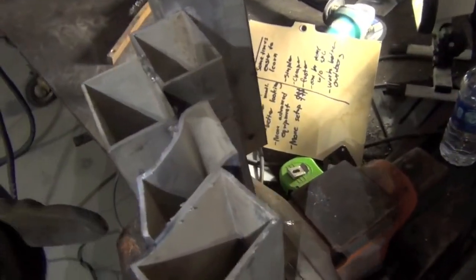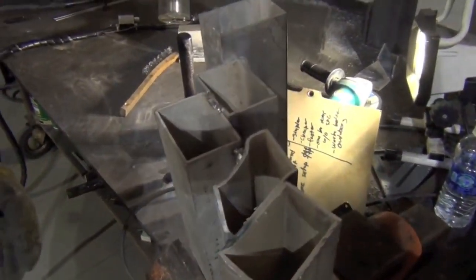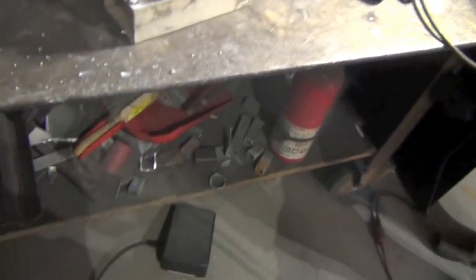Now don't forget, this was through dirty material, and on TIG we tried this with fresh material or cleaned material to the best of our abilities. Here we didn't even try hard. We just brushed it off with a glove so that the loose particles, the sand and the dirt fell off. We didn't even hit it with the wire brush to attempt to break the oxide layer. This about concludes the video.